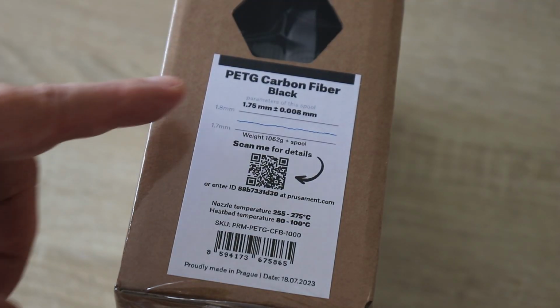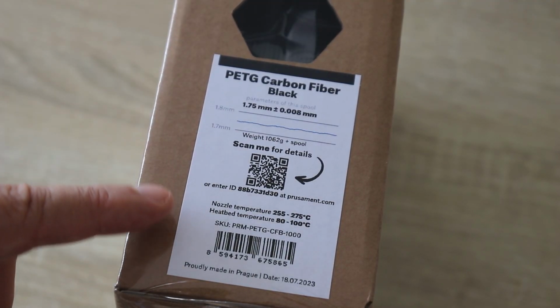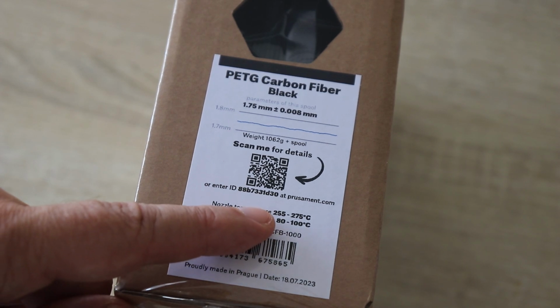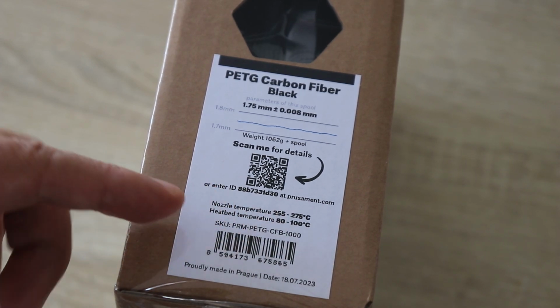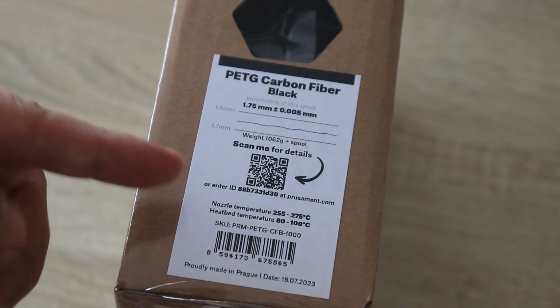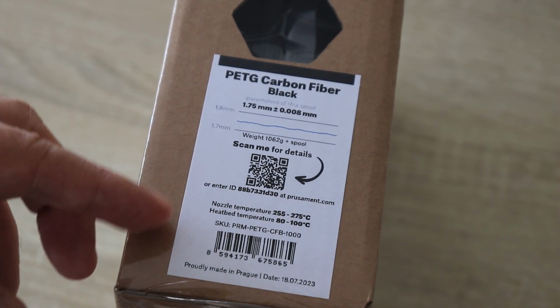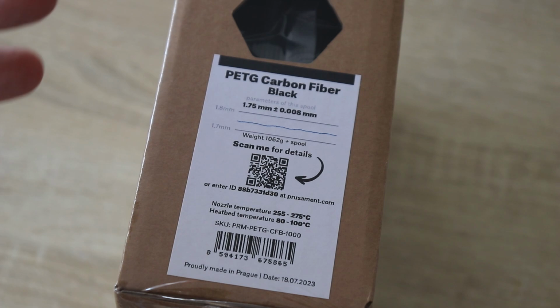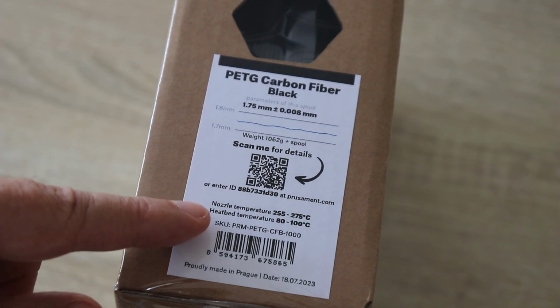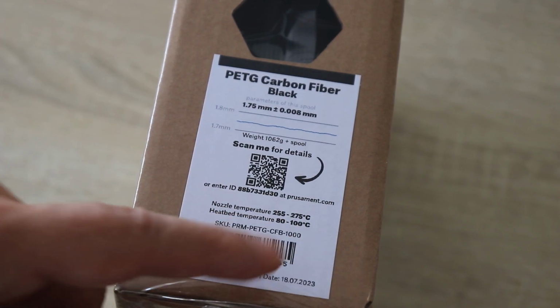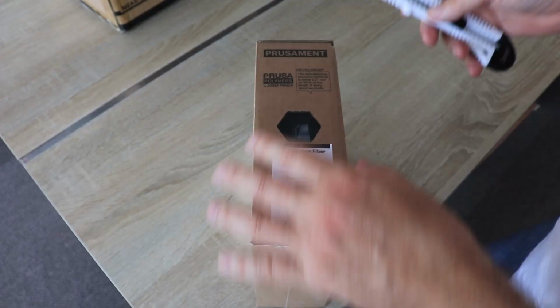I'm starting the printing with the carbon fiber version, and the recommended print temperatures are between 255 and 275 degrees Celsius, and I hope they take into account that this requires a hardened steel nozzle, which actually requires a little bit higher print temperatures, and a heat bed temperature between 80 and 100 degrees Celsius. Let's start with the unboxing of the carbon fiber version.